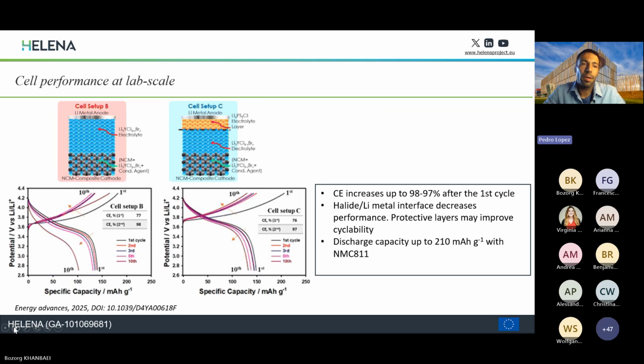All right, so here's some results on the cell performance just at lab scale. So that means we take the materials, we assemble them in a small coin cell configuration, and we do the electrochemical testing in order to assess the performance of the materials. So here you can see some different setups with the halide solid electrolyte as separator, a lithium metal anode, and the composite cathode.